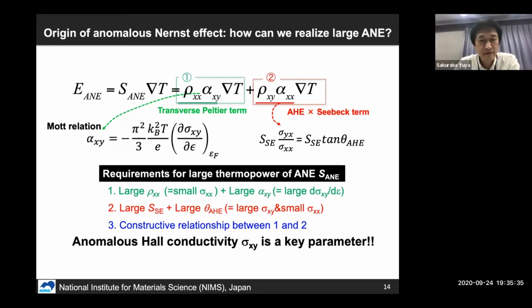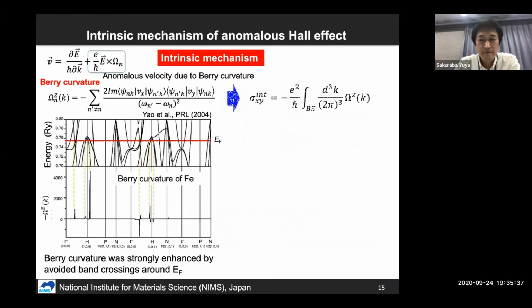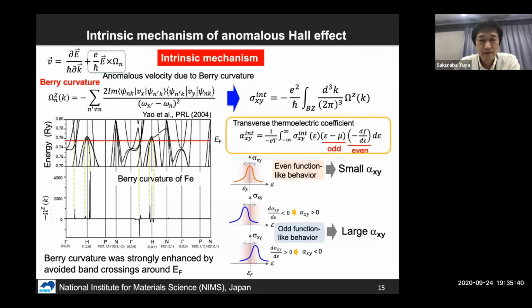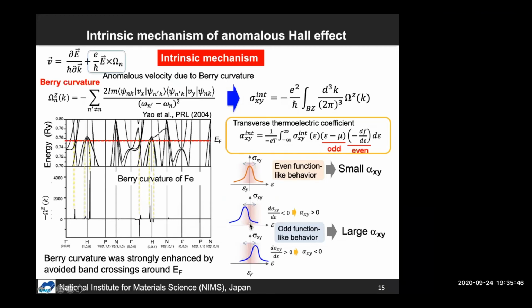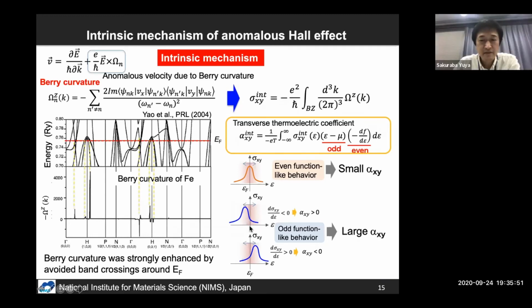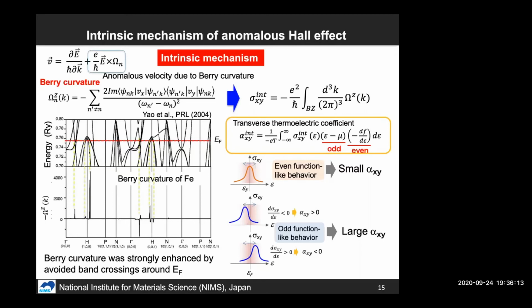Yes, that is correct, because if this sigma xy is 0 at the Fermi level, but the slope of this sigma xy is large, sigma xy is 0, but alpha xy can be large. So even a material having a low anomalous Hall effect can show a large anomalous Nernst effect from the large contribution of alpha xy, I think. Okay, I follow. Thanks very much.